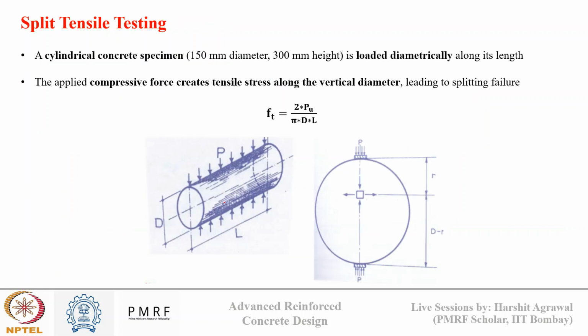Okay, so in split tensile testing, we have a cylindrical specimen of 150 diameter and 300 length, and on the curved surface, we subject it to compression load. So when the compressive stresses are applied, we know this will generate tensile stresses. It will apply external axial forces on the cylinder, and since this contact area is very less compared to a cube, the end platen effect will be very less. So this entire length or diameter of the cylinder will be subjected to tensile loading, and we will see a failure in which the concrete will crack from the middle. So this compressive force creates tensile stresses along the vertical diameter, leading to splitting fracture or failure of concrete.